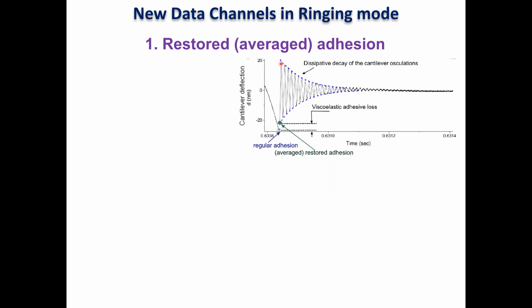Instead of that, we said, okay, let's better quantify the entire curve, and we know how it decays. Actually, one of the fundamentals of this mode, why this mode was even created, is that we saw the Q factor of all these ups and downs is a constant. So we really can apply a damped harmonic oscillator model here. So we can literally extrapolate back in time to the moment where adhesion happened.